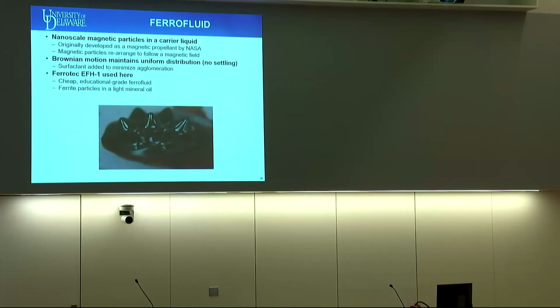And to do this, the colloidal suspensions that I talked about on the hybrid material were larger particles that tend to settle to the bottom of the fluid. But for something like the pump design, we instead want more of an equal suspension, having the magnetic particles suspended in the liquid. So we looked at an alternative magnetic fluid known as a ferrofluid, which is nanoscale magnetic particles within a carrier liquid. This was originally developed as a magnetic propellant by NASA, who were looking at having magnetic particles rearranged to propel spacecraft or other different materials.